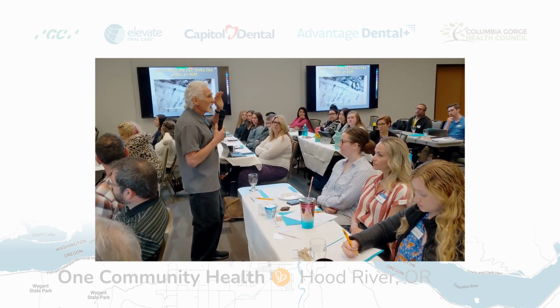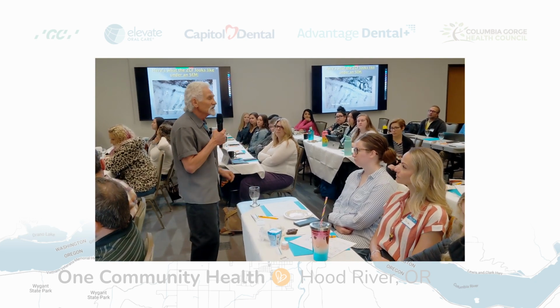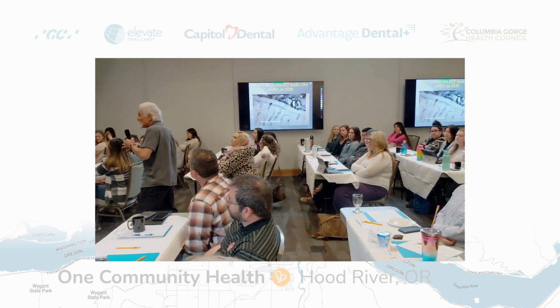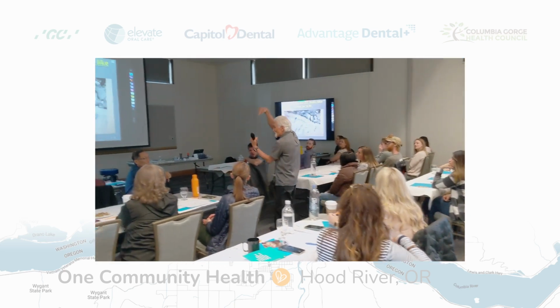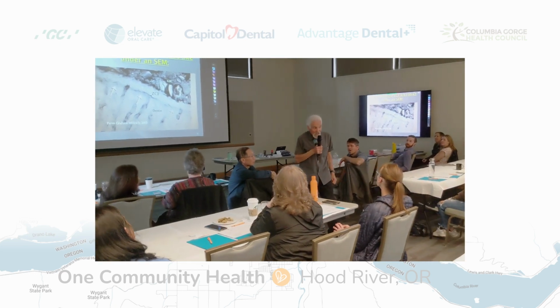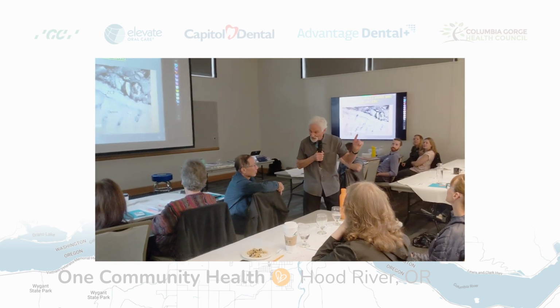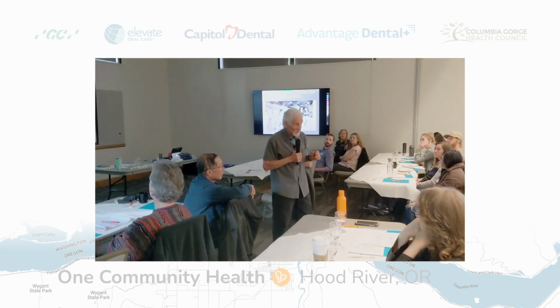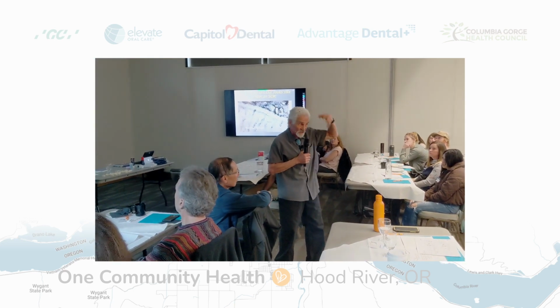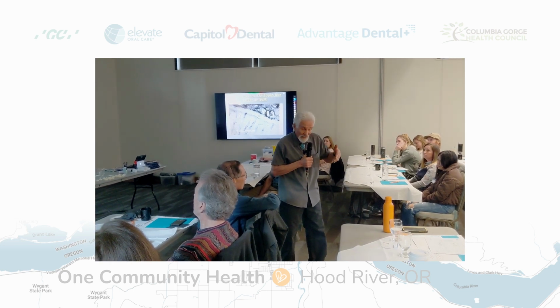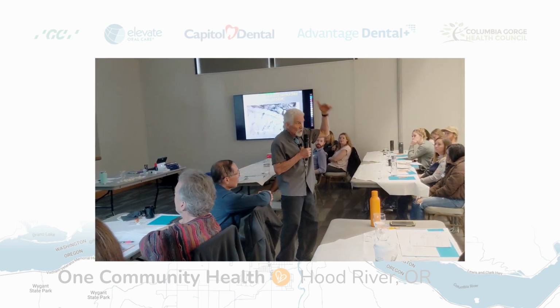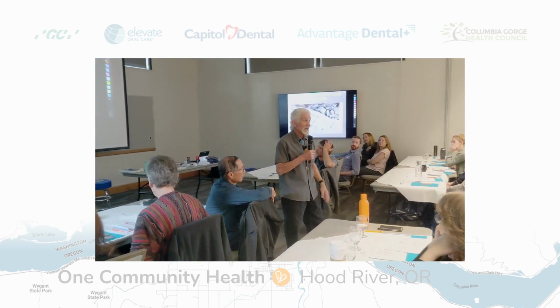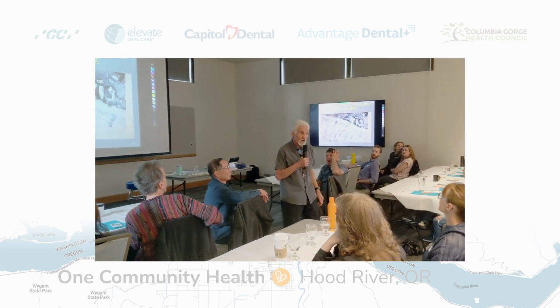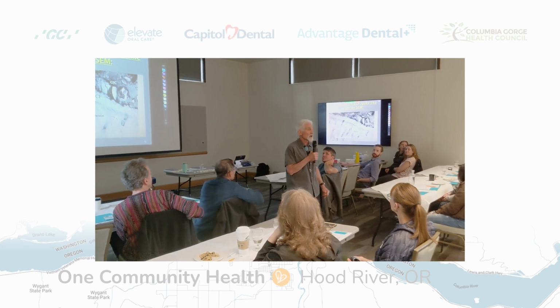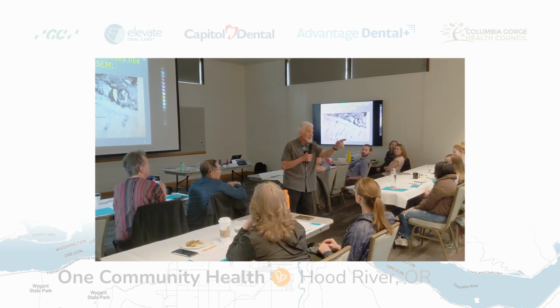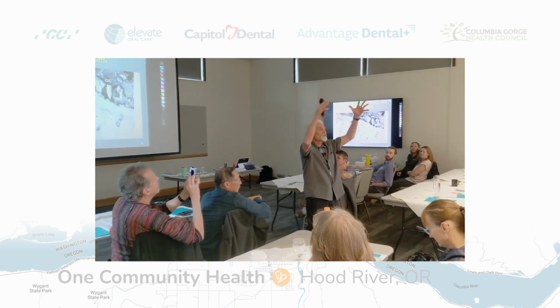But if you use that same resin-modified glass ionomer as a sealant on the occlusal surface where the forces are direct at 90 degrees, they're straight like this, that's weak. That is not going to hold up. It will hold up much better if you light cure it. And over time, in 3 months, if it is able to stay there, because your occlusal forces may not allow that. Depending upon their occlusion, it may just rock that out of place. I'm sorry, that's just occlusal forces. They're pretty darn strong, forces of mastication. But if you don't light cure it, you don't have a chance in hell. But under a crown, it's fine because the forces are distributed through the crown.